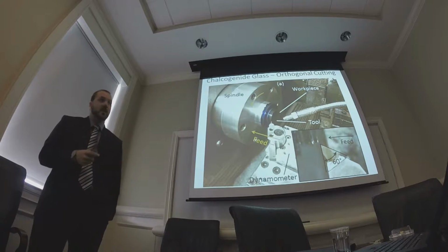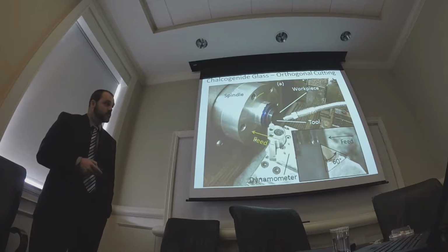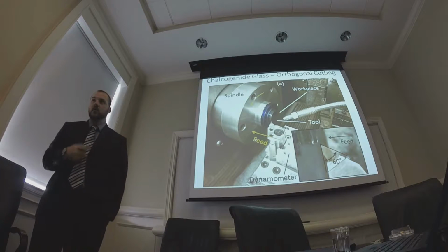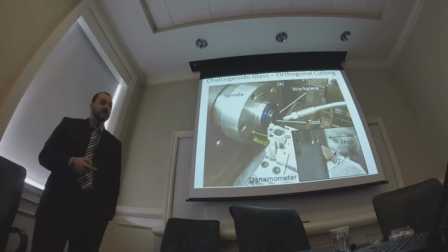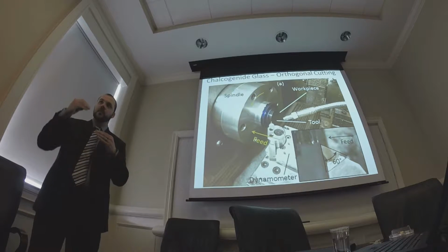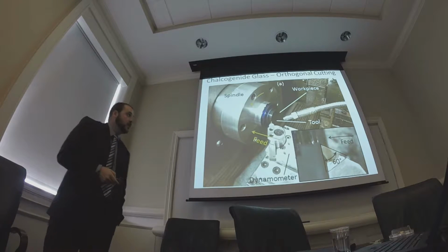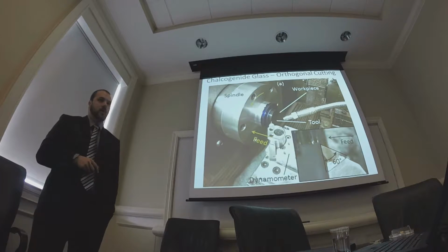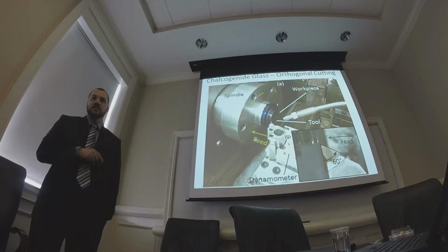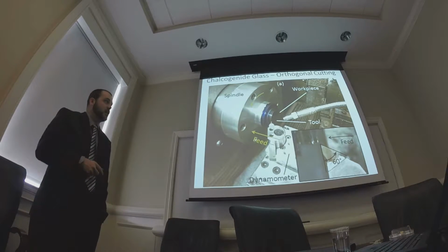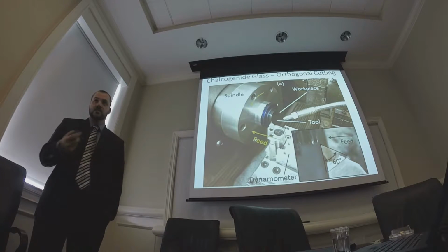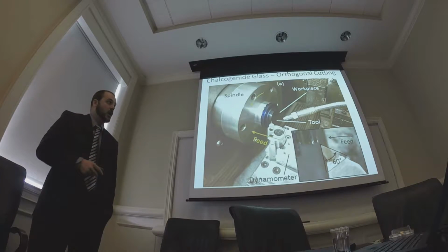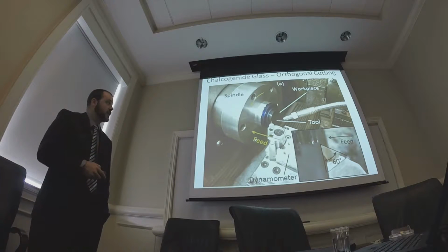And what that does is it creates a constant chip thickness along the width, with the force going perpendicular to that. So it creates the most simplified geometry, where we can just investigate what is happening due to the chip thickness, and then we could adjust the width, and all that should do is scale the force linearly with the width. So we picked a width of 200 microns, and we kept that fixed through all the testing. We did a couple at 500 just to show that yes, it was linear, but I'm not reporting any of that here. Spindle rotations this way.